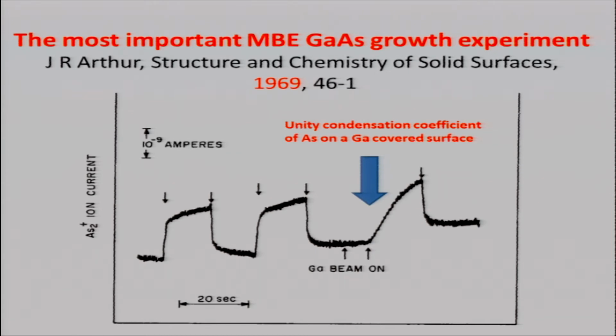Notice here what is showing is the arsenic atoms coming out of the surface when you open the shutter, as a function of time, with that curve here. Abrupt change going up there. That means A is not 0. Not all the arsenic atoms stuck on the surface, and on and off he shuttered. The important thing here, when you turn on the gallium beam on the surface, you have a gallium-covered gallium arsenide surface. Now, when you open the shutter, look here. The exponential curve starts from the beginning. There's no abrupt increase there. That means A equals 0. Unity sticking coefficient.